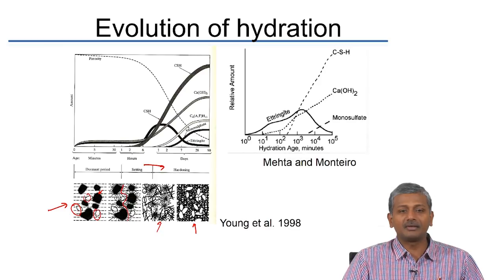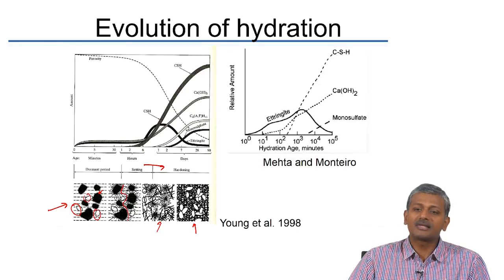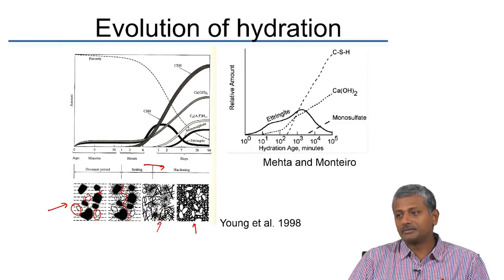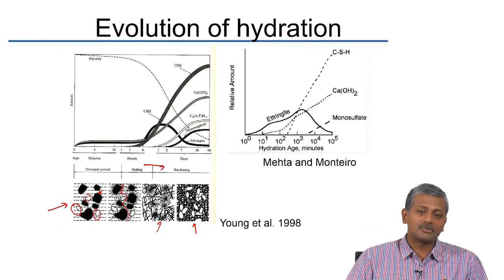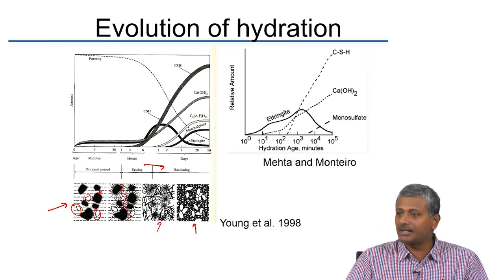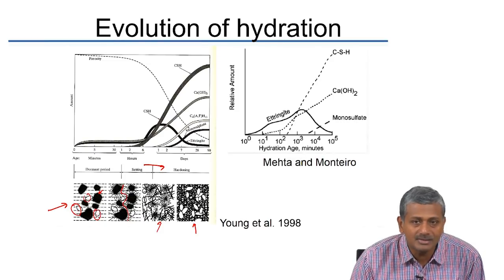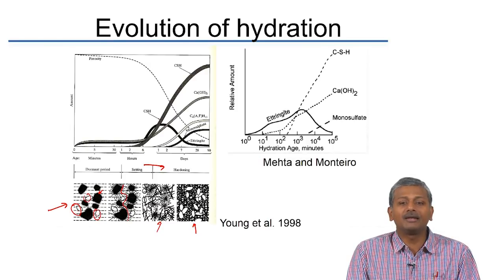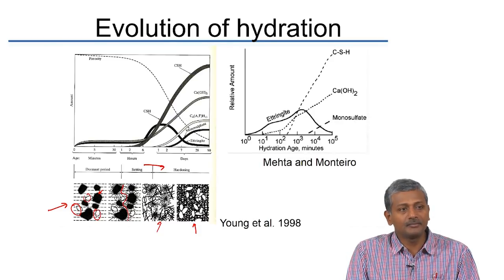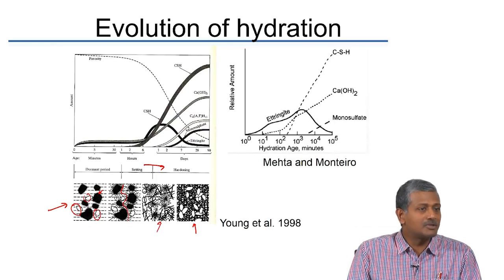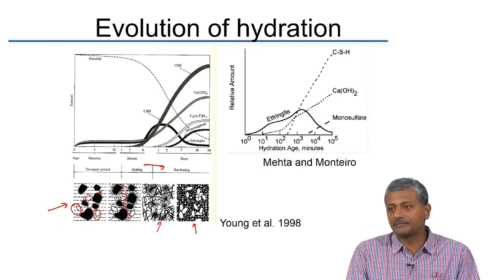When the water-cement ratio is lowered, from the diagram it is clear that the degree of hydration should also be lower. Nevertheless, strength increases. Strength depends on the extent of solid material present and the reduction in porosity. Sufficient hydration is needed to seal porosity, but not all cement particles need to react — they still function as fillers even unreacted, blocking empty spaces in concrete. At low water-cement ratio, higher strength is achieved even though the degree of hydration may be much lower.